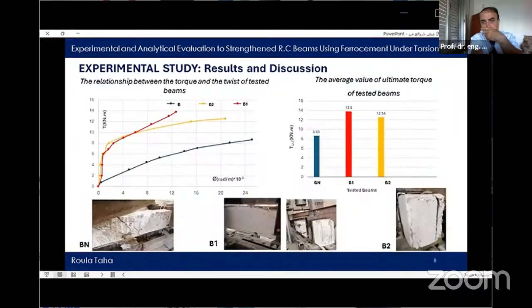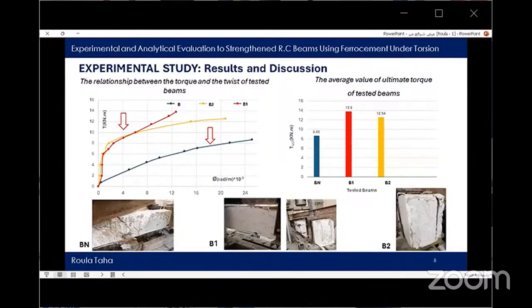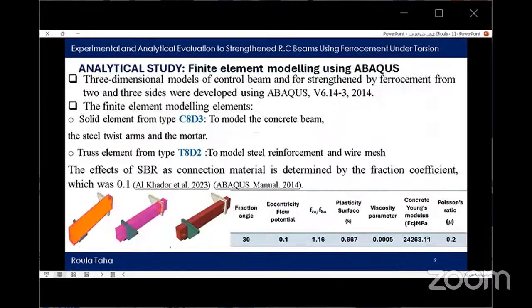From the figures, we can notice that the control beam torque-twist relation displayed linear behavior, while the curve of the strengthened beams is characterized by 3 stages. Also, it is clear that the torsional behavior of the strengthened beams and cracking control ability have improved. The growth of cracks is reduced. 3-side wrapping maintained its connection with RC beams with only minor cracking, while the ferrocement laminates with 2-side wrapping showed partial slipping with semi-deep cracking.